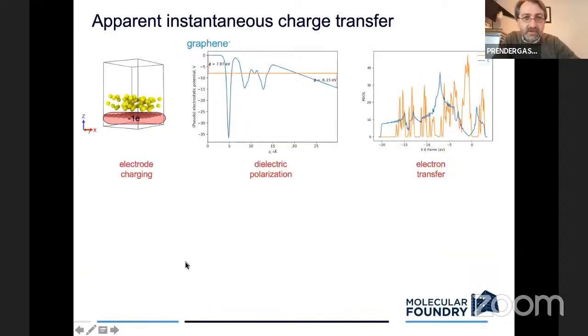But what we were noticing as we increased the amount of sulfur is that we began to see something that didn't seem physical. So there's an instantaneous charge transfer of the excess electron that we've added to the system. So stepwise, what we think should happen is you charge your electrode. Since you have a dielectric medium now, before you get to the electrolyte, which I haven't shown here, there will be a polarization induced in the dielectric that will screen the electric field, but the electric field will still penetrate through. And then what you'll find is that the electronic structure of the dielectric and the